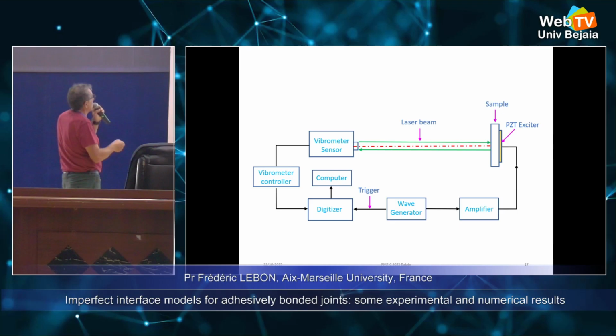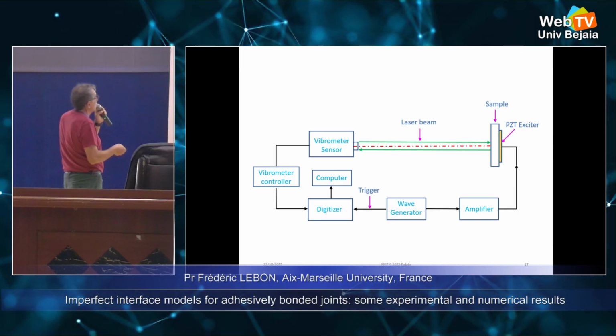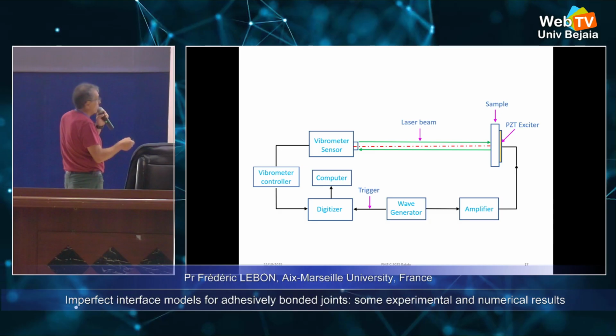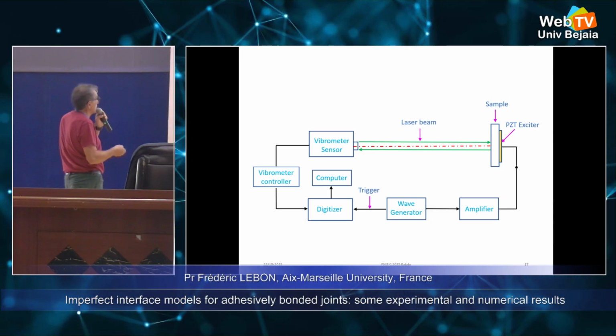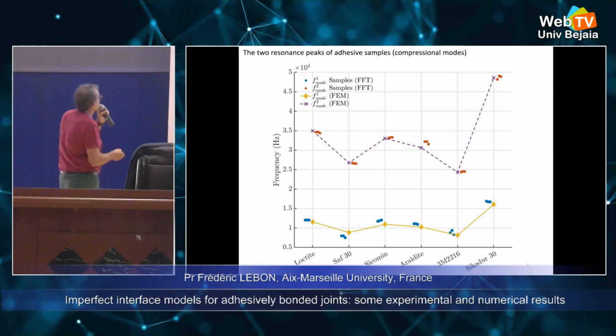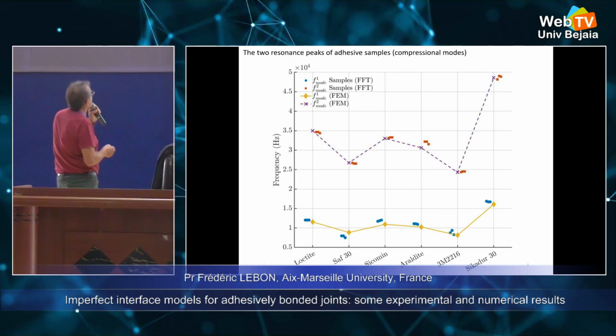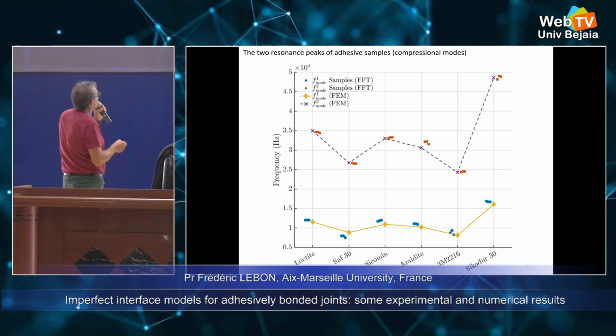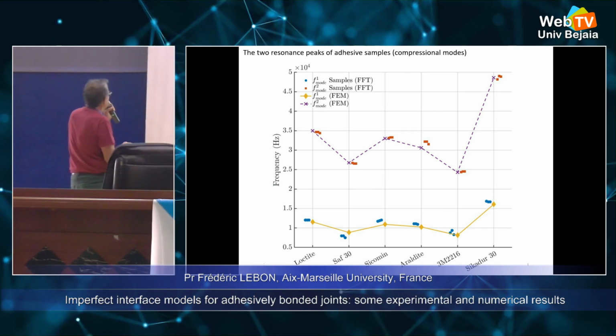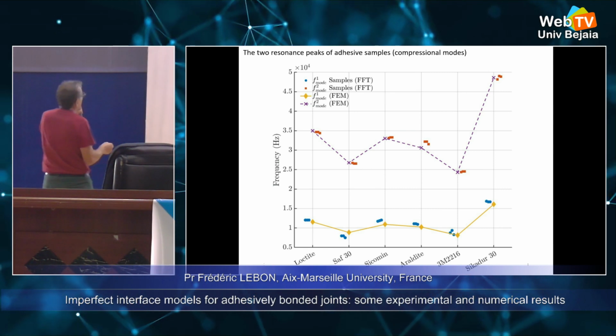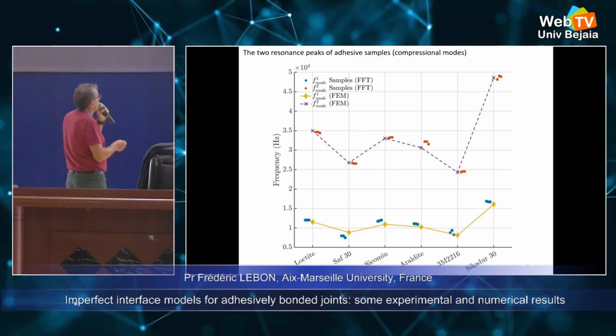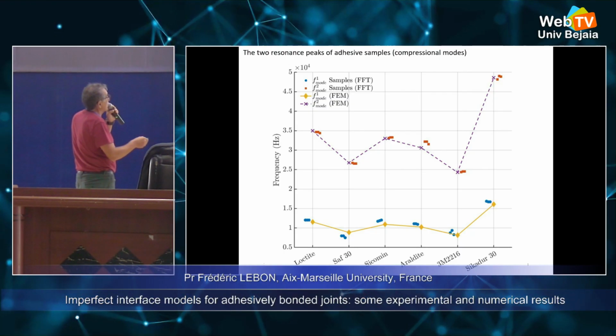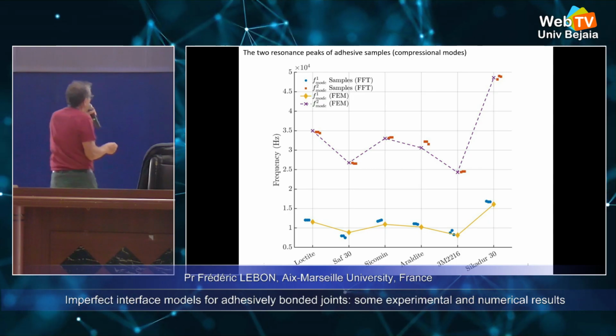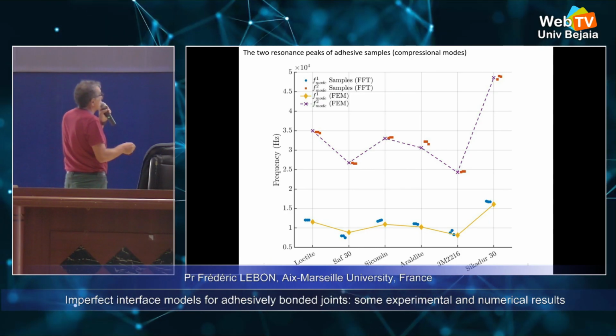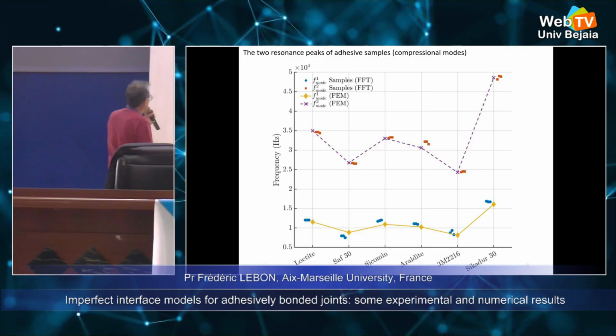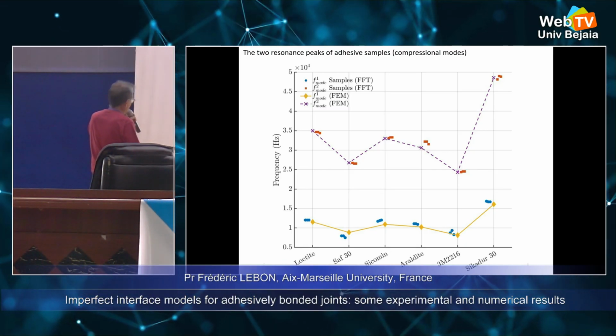This is the experiment. We use a laser to measure. There is a piezoelectric material for the excitation, and we find the modes. Here there are two resonance peaks in compression. Here in this zone and in this zone, and we can compare the experiment with three samples for each experiment, and we can compare with the numerical results we obtain with finite elements. Okay, for the 6 glues.